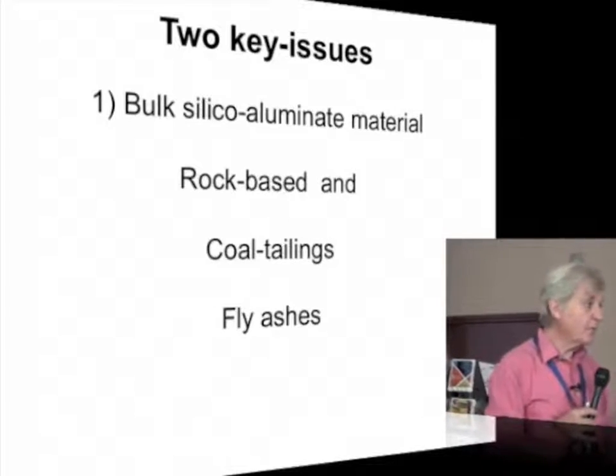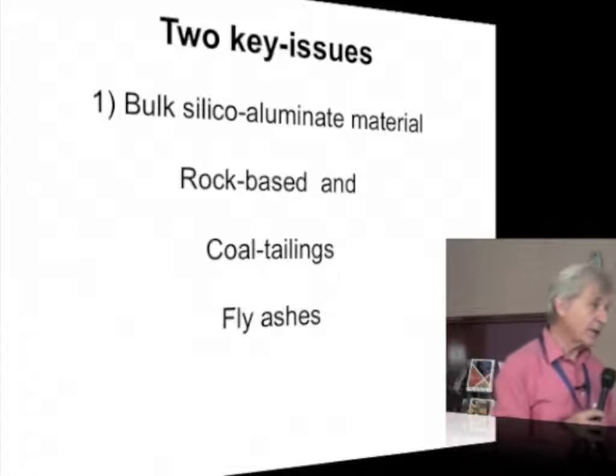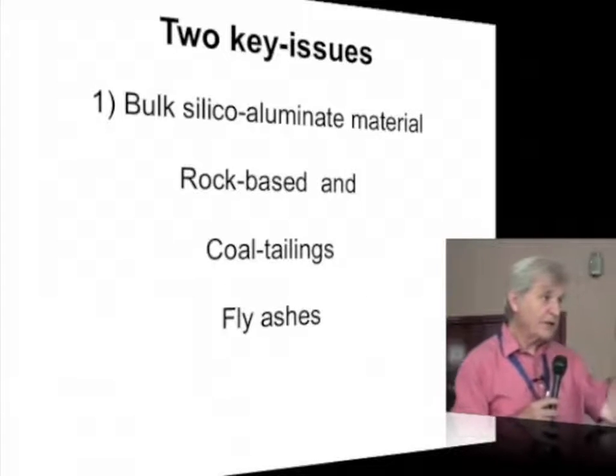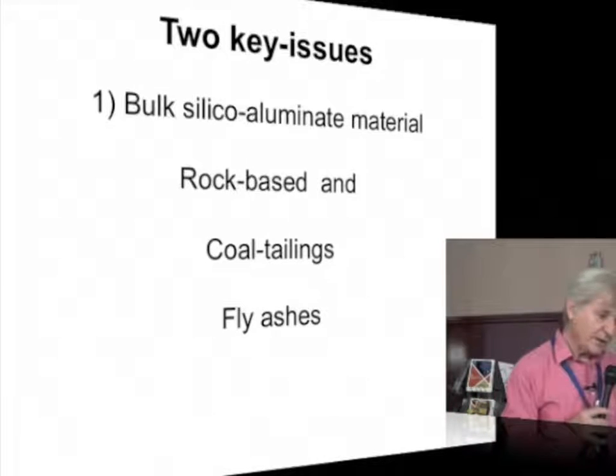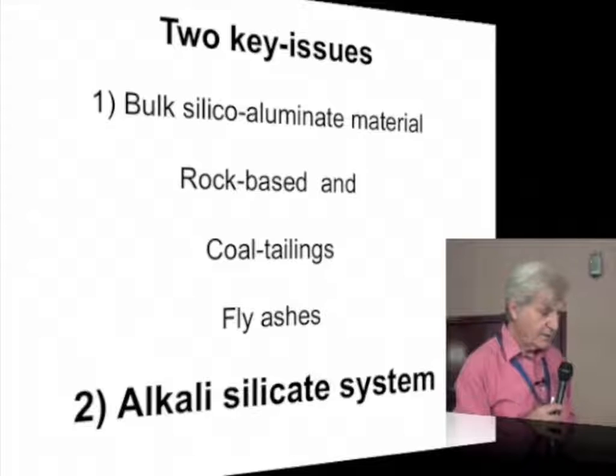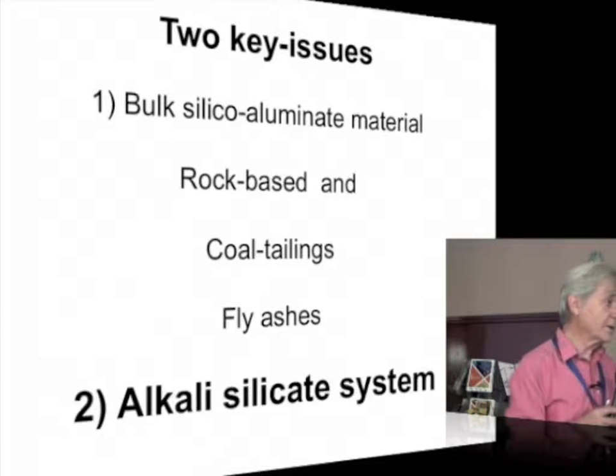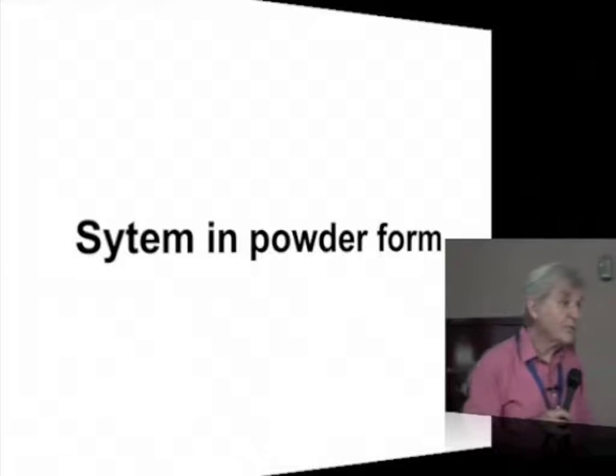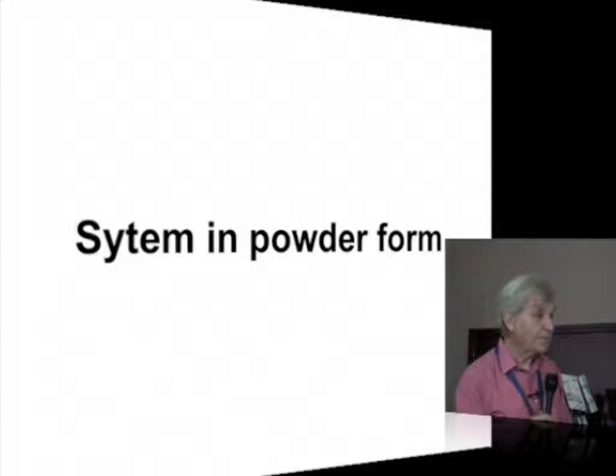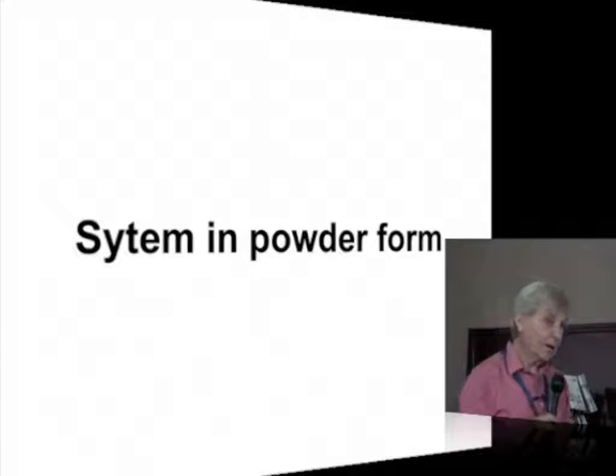So you remember we said we have two key issues to tackle the problem of mass production. Millions of tons. The bulk silico-aluminate material is easy to get, but the alkali silicate system is not easy to get. So we have to make a system in powder form that will supply in the mix a low pH, a user-friendly system. I don't want a powder form that is made of NaOH, powdered, or metasilicate, molar ratio 1:1. I want something that has a molar ratio of 1.4, 1.5.